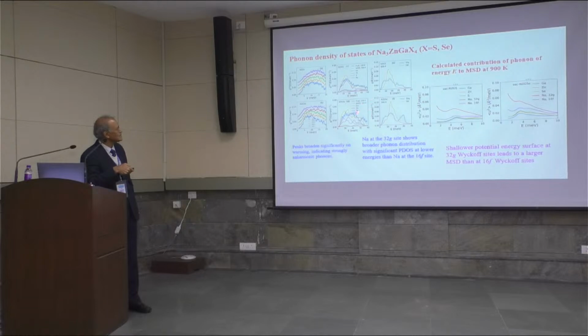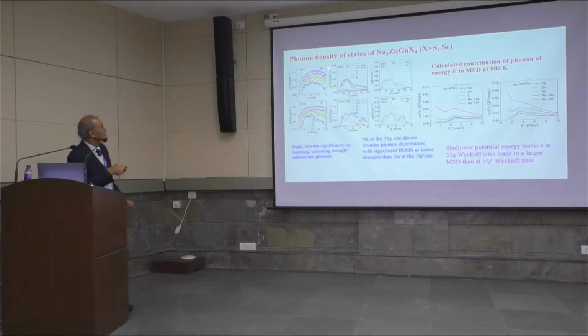The different atoms. Okay, sodium, selenium, gallium, and so on and so forth. What we identified here is that the key phonons where the significant broadening takes place are associated with the sodium atoms of one type, 12g, that means we just call sodium 1 and 2. So that has a large broadened structure, whereas the other one has very sharp structure.